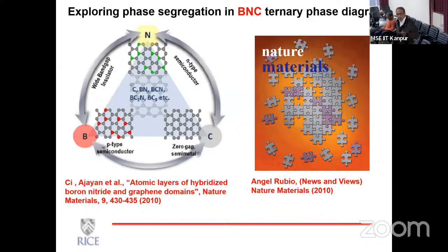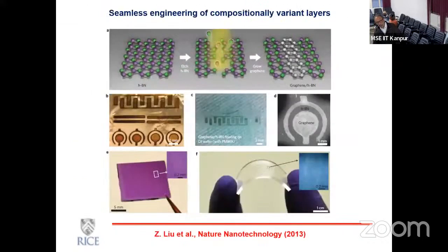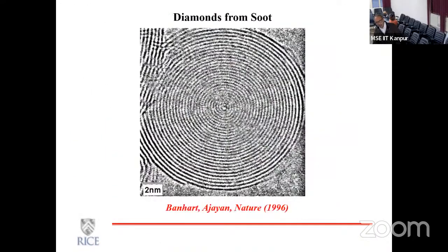But what we also realize is that when you're trying to bring multiple components together and build structures, they can also have local phase separations and so on, which becomes very problematic. So if you're trying to grow a boron, nitrogen, carbon material, you have these segregated domains of boron nitride and carbon. And again, it has its benefits, but it's also interesting from the point of view of controlling materials at the atomic scale. So let me skip these. This is the final experiment that I will show you.